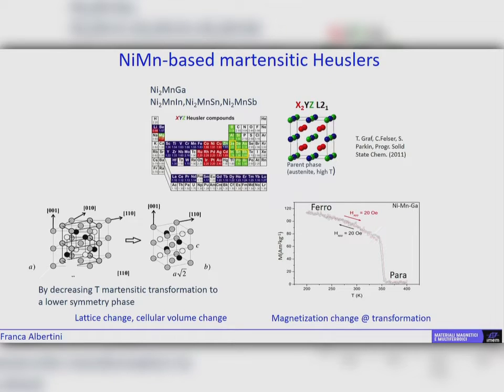The first and the main is a Martensitic transformation, that is a diffusion-less solid-state transformation from a cubic high-temperature austenitic phase to a less symmetric, let's say, tetragonal or orthorhombic or monoclinic low-temperature Martensitic phase that depends on the composition. On the other hand, these two phases can be magnetic or non-magnetic. Here, for instance, in these thin films of nickel-manganese-gallium composition, we have a direct transformation from a ferromagnetic monoclinic martensite to a paramagnetic austenite.